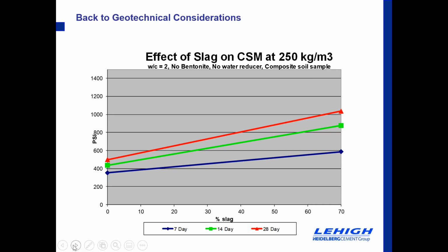And for numerous reasons, you could hypothesize the organics, every bit of the soil changes. We do know as the soil levels have higher organics in it, it hurts Portland cement more than it does slag cement. And typically, one of the reasons you can consider that is, again, the slag is very glassy and absorbs water much slower, not much slower, but slower than the Portland cement.